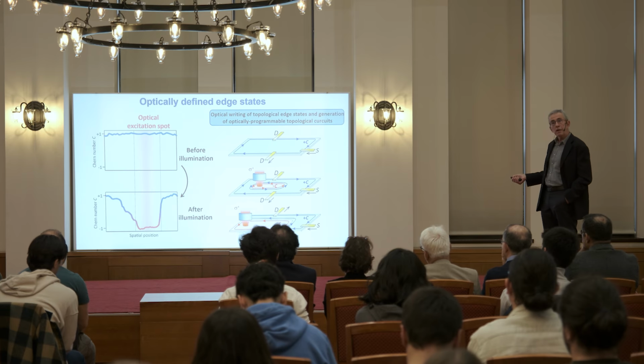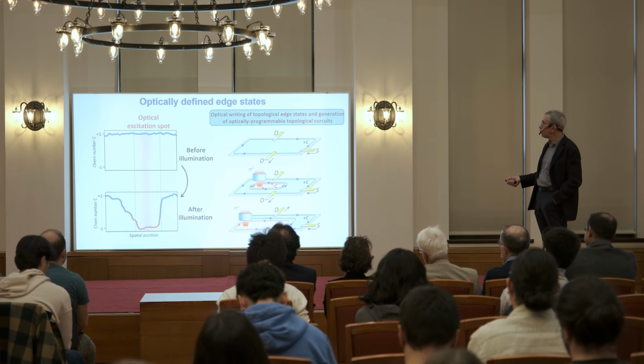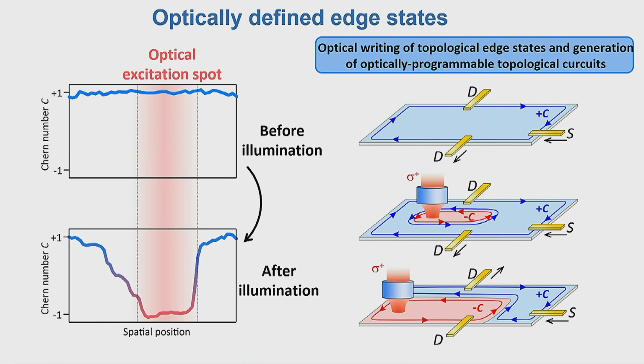All right, so as a potential next step or application, what we can do is we can actually use shaped beams. In this case, this was a simple Gaussian beam. So we prepare the holes in one Chern state, +1. When we apply our laser pulse, we can flip the Chern number in the region, or the topological integer, to -1 in the region that we excite. In this sort of region here, that's due to defects in the system. We probably have different puddles with different Chern numbers. That's why it looks like it's a continuous change. In an ideal system, this will be flipped between one and the other. And if we can get such high quality materials, we can define topological circuits all optically.